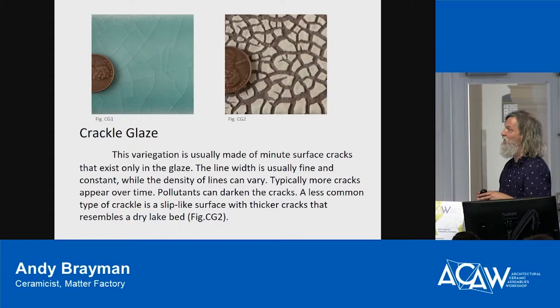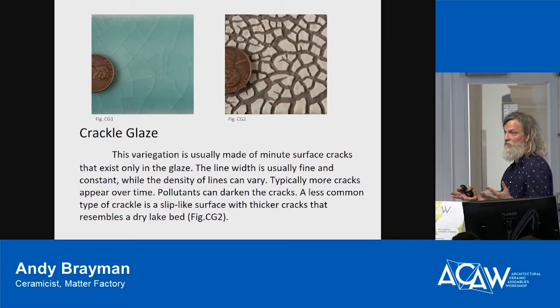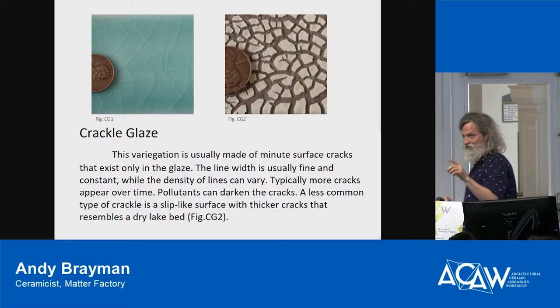In terms of Boston Valley, their clay body is tuned to survive freeze-thaw. And so if there's a crackle pattern on the glaze, it's nothing to worry about or concern yourself about. It does not mean that the crackle is happening because there's structural flaws in the body itself. If you don't understand ceramics, it's a reasonable question. Thankfully, the answer is not a problem. The way it works, and Bill and I could tag team this lecture probably,